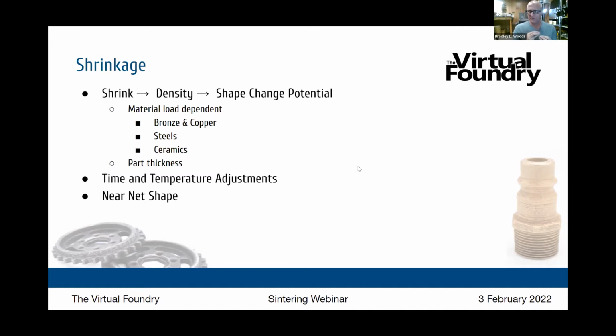And so when you take, for example, a copper part and you debind it and you remove that plastic, there's space where the plastic used to be. So something has to happen. Something has to occupy that space or it'll just fall apart. And what happens is during the debind phase, the part will shrink somewhere in the area of 2 to 3%. At that point, you have a part that is made up of particles that are all touching one another. And there's a little bit of binder remaining, just enough that you can handle it in the brown state. From there, the next step is to sinter it.